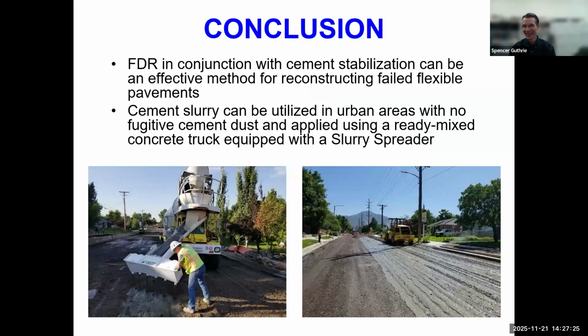All right, here's my concluding slide that I would like to share today. Full depth reclamation in conjunction with cement stabilization can be a very effective method for reconstructing failed flexible pavements. And in particular, cement slurry can be utilized in urban areas with absolutely no fugitive cement dust. It can be applied using a ready-mix concrete truck, which is available almost anywhere, and equipped with a slurry spreader.